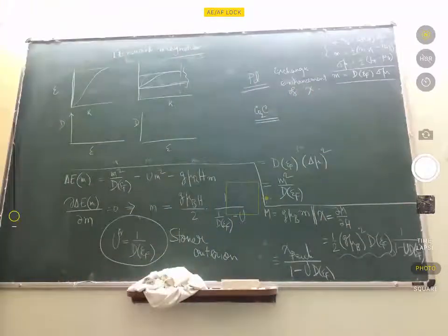The susceptibility is enhanced because of this effect, and as a result, even small perturbation can cause huge response in the system. In fact, what happens is that if you put a single magnetic impurity in palladium, let's say iron, because it has a large chi, the response is large, and a large part of the system actually gets magnetized because it has a large susceptibility.